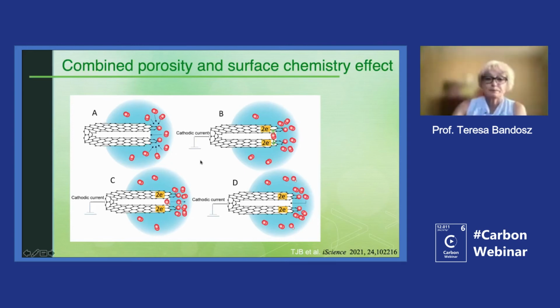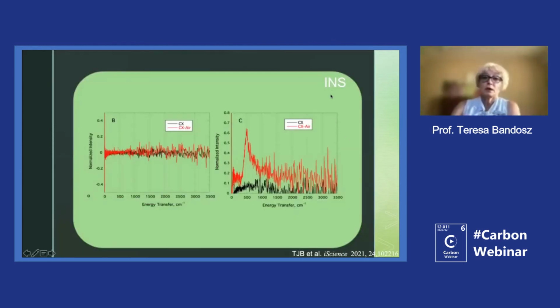But this might also help to visualize the question I have, whether it is an intensive or extensive effect. Because you see, the oxygen has to be close to water. So really the volume in the pores is not so important. What might be important is the number of those very small pores. And here it may also bring us to the effect of the defects, where, if we have defects, they cause a kind of valley in the graphene layer, so maybe this effect is similar. Then we did inelastic neutron scattering, because we wanted to see if the carbons are really able to give us those OH groups even without any potential.